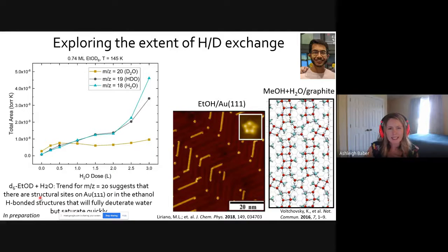One interesting thing he did find was, starting off with fully deuterated ethanol, D6-EtOD, if he starts to add just a little bit of water on the surface, or we just have background water on the surface, you see an increase in fully deuterated water. So there are two exchange processes happening on that water to form D2O with a mass to charge ratio of 20. And that's the first thing that's seen, basically. And then this kind of levels off.